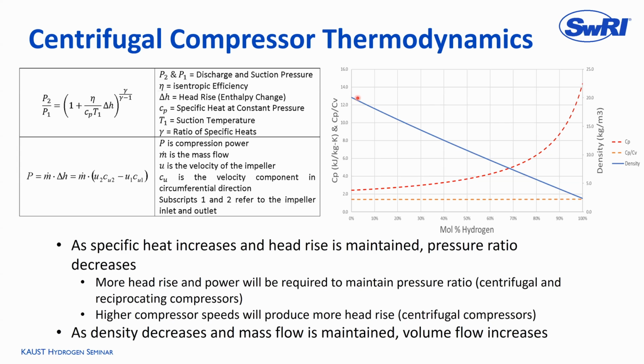The other point is about density. So the density goes way down as you add hydrogen. So even though hydrogen is more energy dense on a mass basis, at pipeline conditions, it's actually significantly less energy dense on a volume basis. Compressors are all volume flow machines. So as you increase the required volume flow in a pipeline, it goes up by a factor of about 3. Then you're going to need larger compressors or compressors in parallel to handle that kind of volume flow.